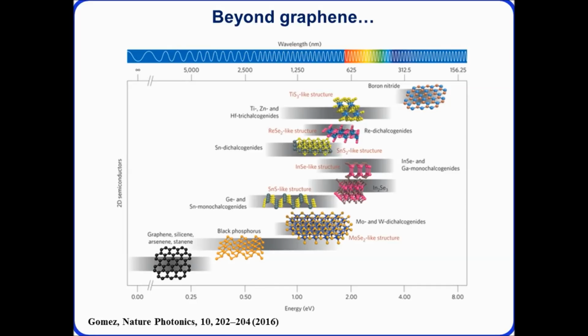So again, this is highlighting another subset of these structures. We have graphene down here, which can actually absorb all wavelengths of light, but we have this middle range here, and we have the insulating boron nitride at the end here, which is absorbing in the UV because it has quite a large band gap. So there's many other materials in this regime that we want to play with, and we are playing with, which have many important applications, specifically in the electronic field and also optoelectronics. So they interact with light differently, and they can provide useful combinations with graphene and other materials.